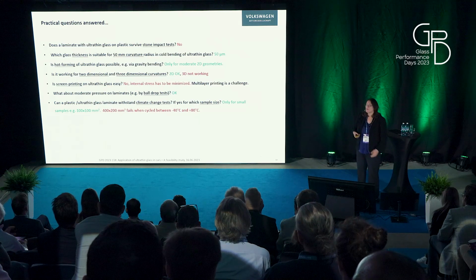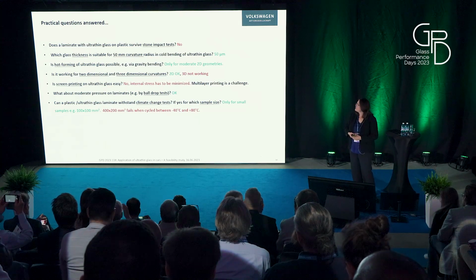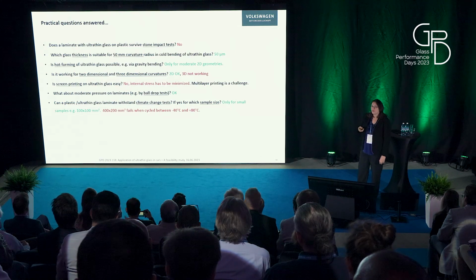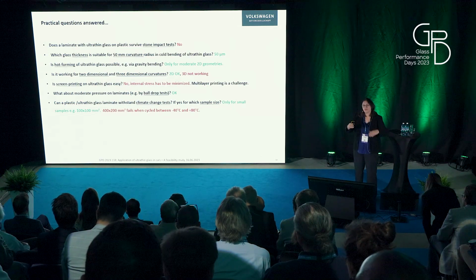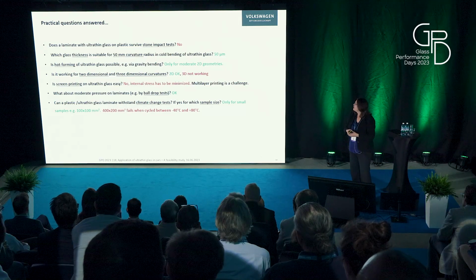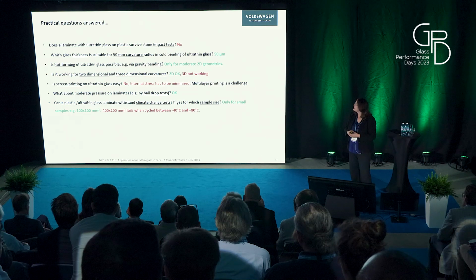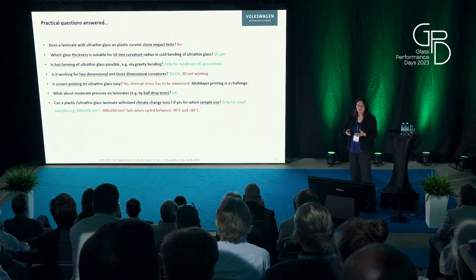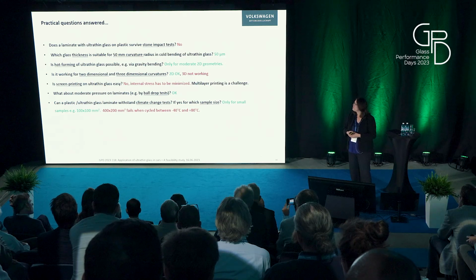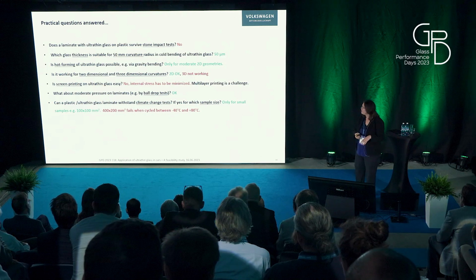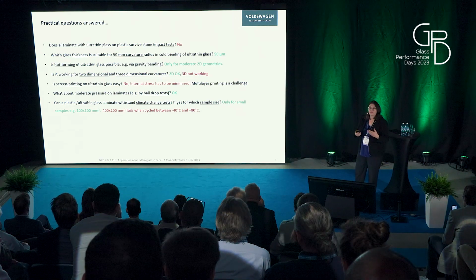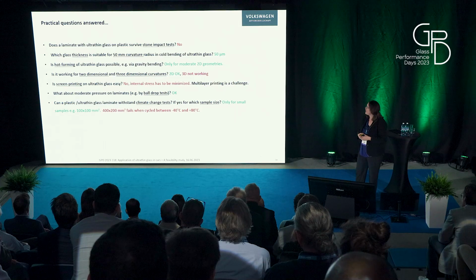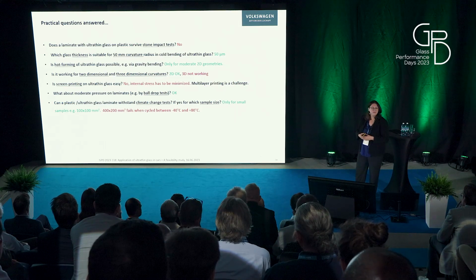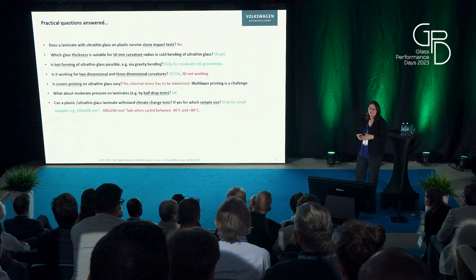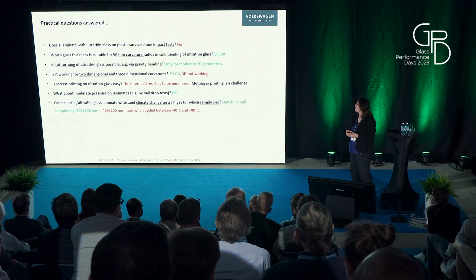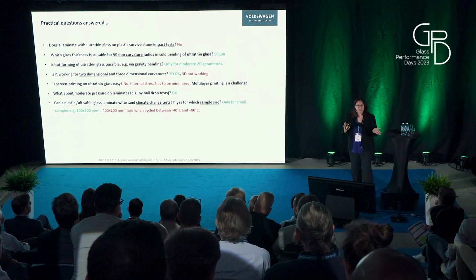Yeah, so to summarize my talk, we could answer some of these questions. The stone impact test was not passed. The glass thickness for such small curvature, like 50 millimeter, the best choice would be 50 micrometer here. Hot forming is especially possible for two-dimensional geometry. Three-dimensional is still something we have to work on. And screen printing in principle is fine as long as you choose the right inks. So ceramic inks, for example, are not working very well. You have to go for organics. And well, the ball drop test, I would say it was quite fine.